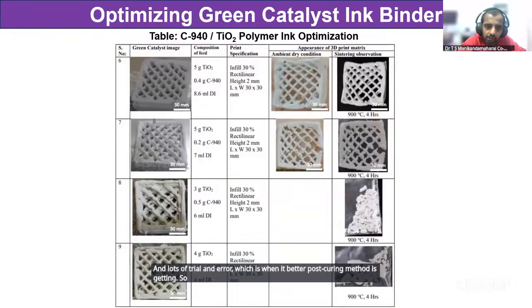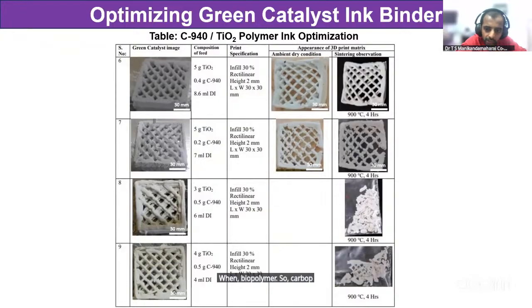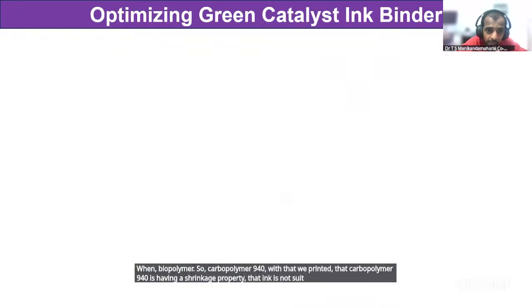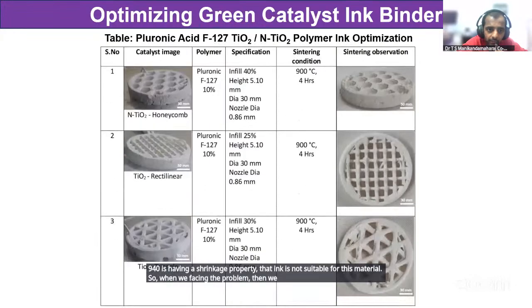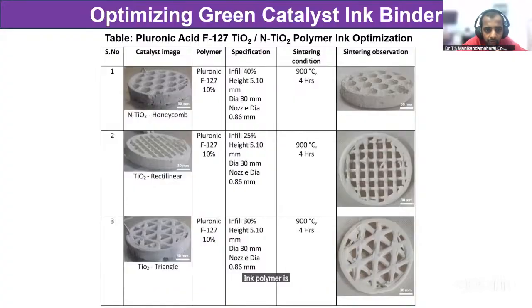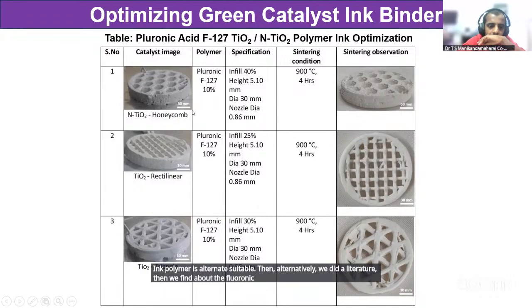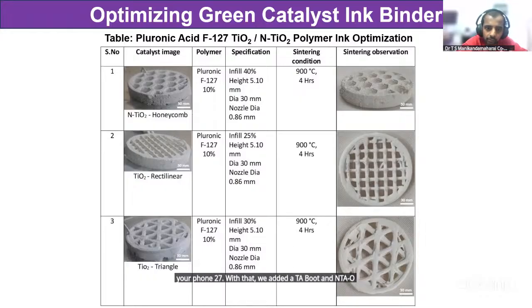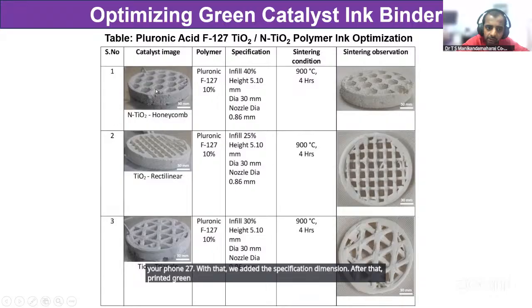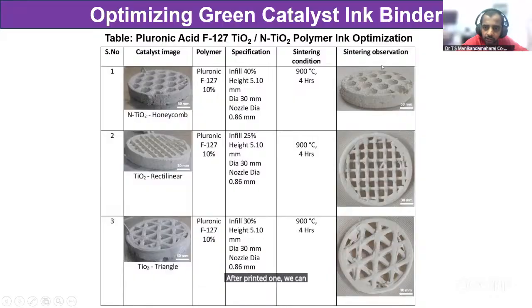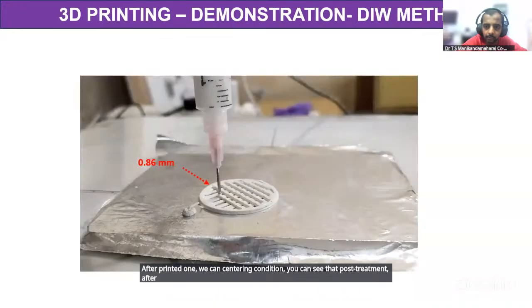Here we took one biopolymer, Carbopol 940, to print with. Carbopol 940 has a shrinkage property, so that ink is not suitable for this material. When we faced the problem, we looked for an alternative suitable ink polymer. Through a literature search, we found Pluronic F127. With that, we added TiO2 and NTiO2, then printed the specified dimensions. After that comes the printed green catalyst. The green catalyst ink is in the left column of the catalyst image. After printing, we apply the sintering condition, and you can see the post treatment in the right column of the images.